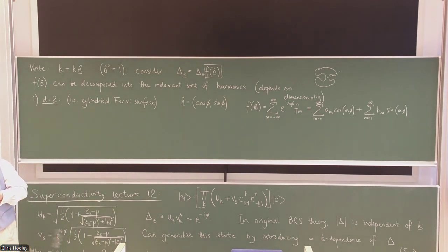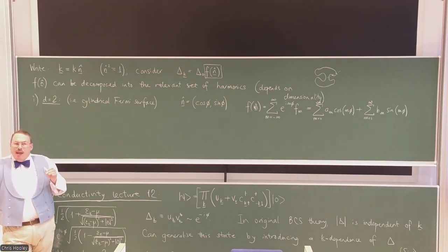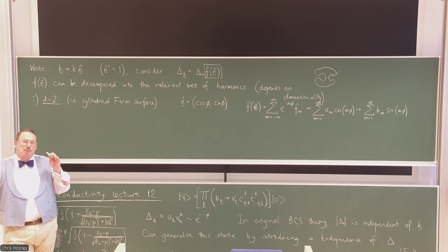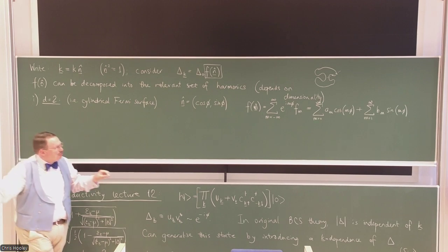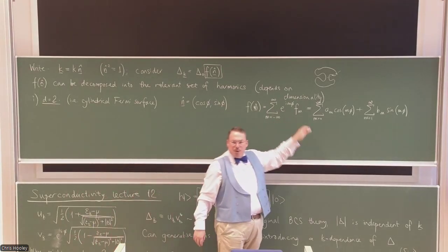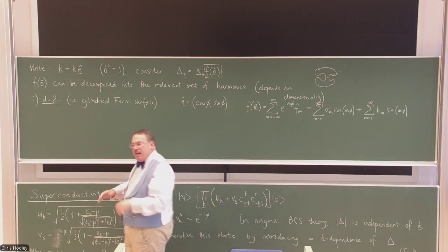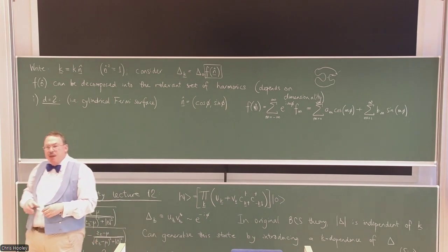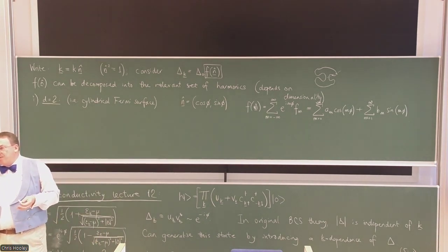So this idea of classifying by harmonic actually only works perfectly near the critical temperature. In fact, it only works perfectly at the critical temperature. So it is generically the case that as you cool your sample, one of these harmonics will set in first. That's the superconducting transition. So right at TC, you will usually have a pure single harmonic form of the order parameter. But as you cool below TC, higher harmonics tend to mix in. You see exactly the same with other forms of order, right?